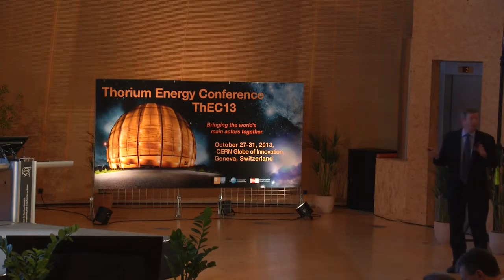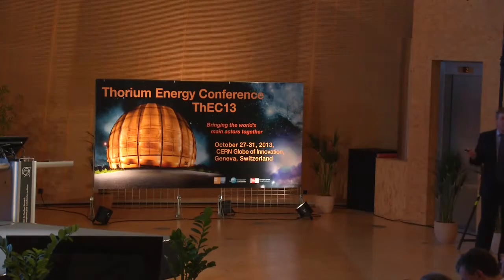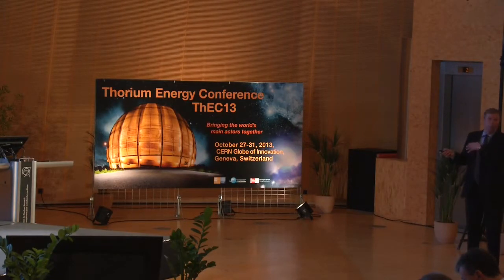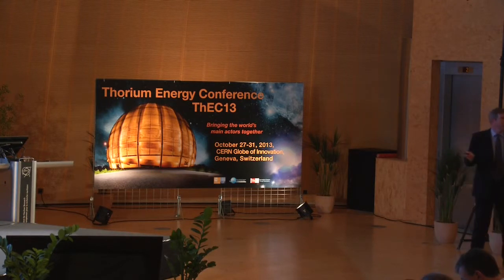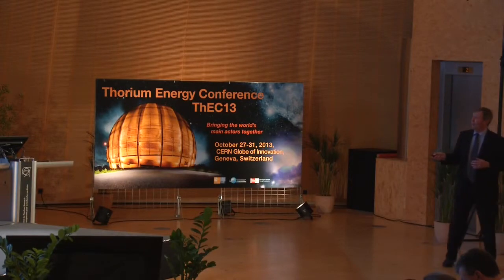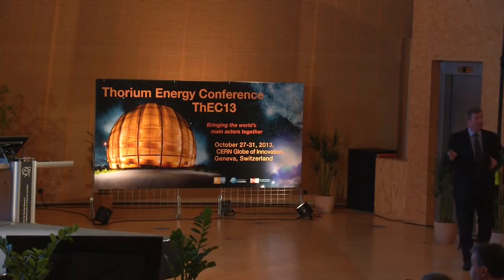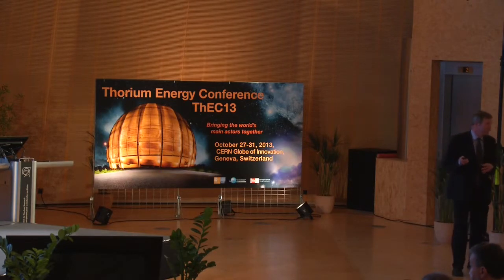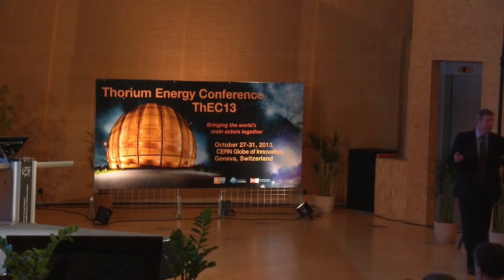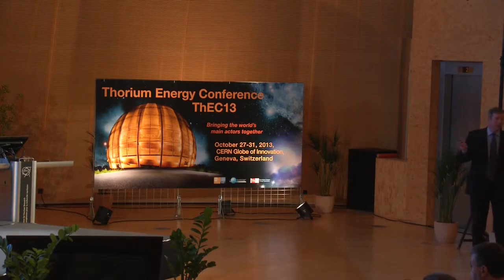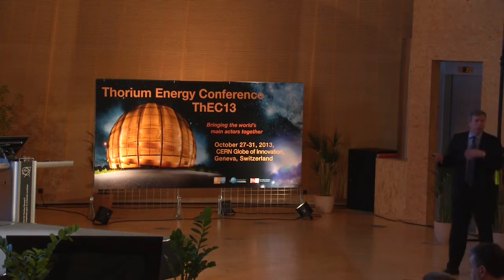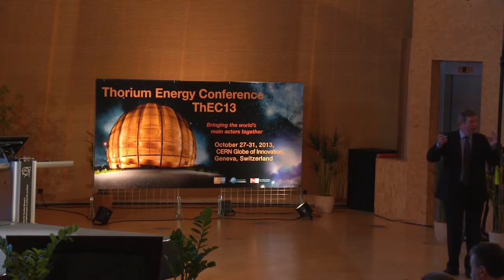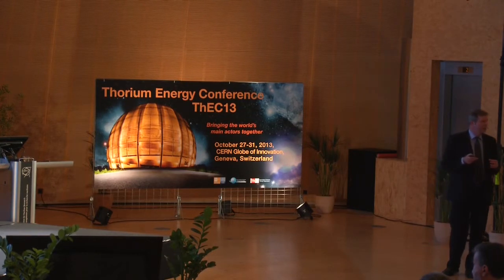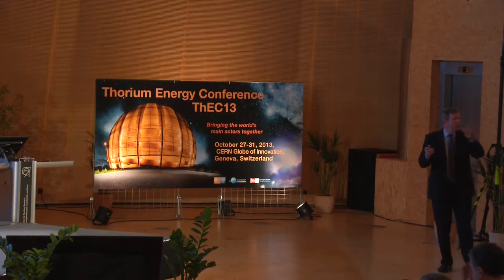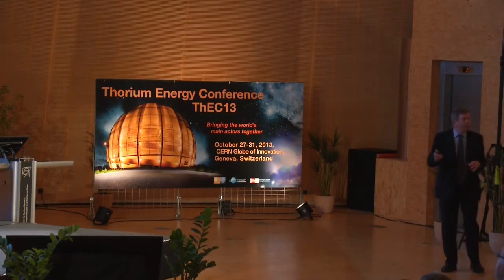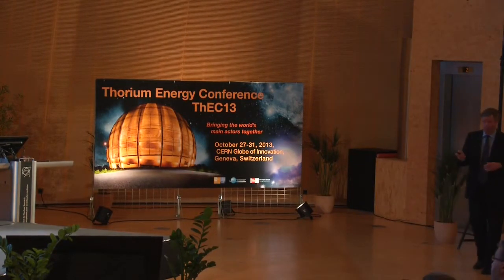A big advantage of doing this is that it's a general methodology because it's based upon basic principles. So I can gain confidence in the way this will work, say, for lithium fluoride, thorium fluoride, from the work that we've done on other fluoride and chloride systems. It's a general methodology applicable to a wide variety of ionic liquids. And of course, one of the other big advantages of this way of making predictions of material properties is you don't need a hot lab to do your experiments in. You can work on radioisotopes, and it doesn't damage your supercomputer. So this is a general applicable approach and would enable you to span the whole composition range, which you require here, without direct experimentation. You would need experimentation at certain points, but to interpolate between those experimental points, one could make use of this sort of information.